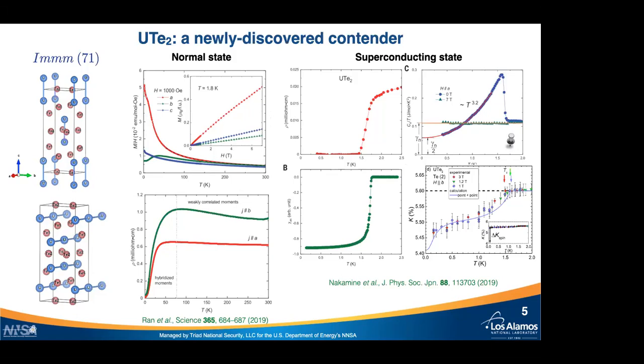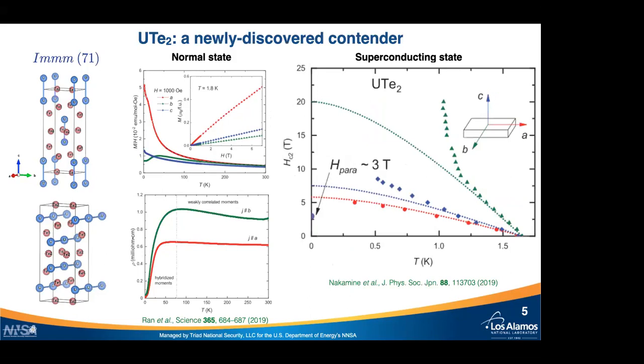And more striking, I guess, at least to me, is this upper critical field plot versus temperature, where for fields along the A-axis, one has a small critical field. Again, fields along the easy axis may do that. However, when the field is parallel to the hard axis, meaning the B axis, the critical field is gigantic. It's much larger than the Pauli paramagnetic limit for spin singlet superconductors. So this is all consistent with the spin triplet superconductor so far. And again, those may be nearby a ferromagnetic instability, which was also put forward in the first Science paper.